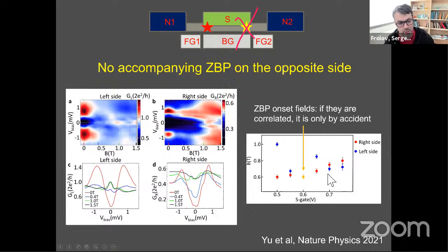So this plot summarizes that the onset of the peak on the left and on the right, the red and the blue dots, are different. There is accidental coincidence sometimes, but there is no statistical or consistent meaning behind this. It's just accident. So I could, in principle, tune to this gate, show you zero bias peaks on two sides, and publish a Nature paper saying that I found two Majoranas. But I have not done that. I published a Nature Physics paper that says I have not found the two Majoranas.